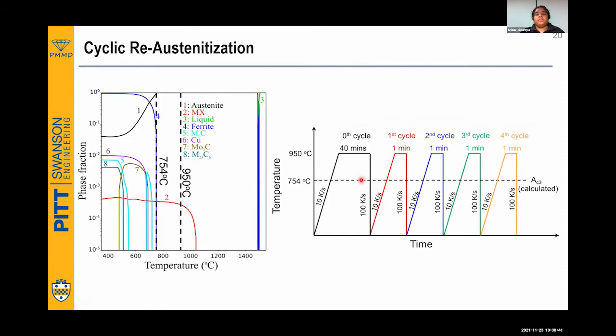We designed an experiment where initially we take it to 950 degrees C, all without pressure, hold it for 40 minutes to make sure that the material has been completely austenitized, and then cool it. Ice water quenching typically has a cooling rate, a ballpark figure, of 130 Kelvin per second. We are trying to cool with a cooling rate of 100 Kelvin per second.